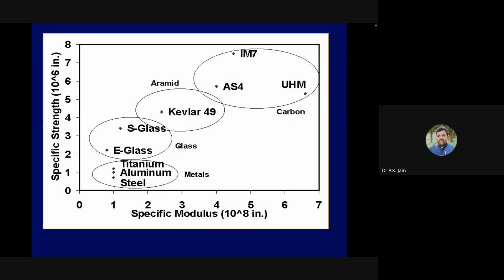Now we'll talk about carbon fiber. Carbon fibers are a very important class of material. If you compare metals, glass, aramid, or carbon, you see metals have very good strength, but because of the high density of metals, the specific strength is low. The specific strength and modulus, in the sense of rigidity, which will not undergo any strain at high load. With a low strain only, it is called a high modulus material. So carbon enjoys very high specific modulus as well as specific strength.